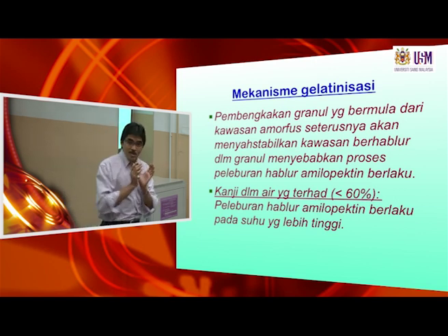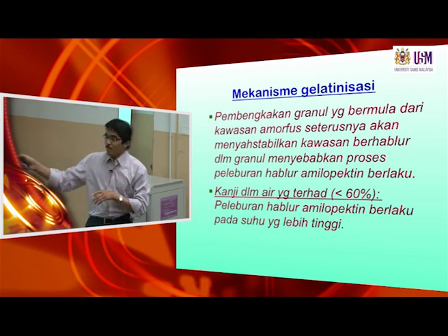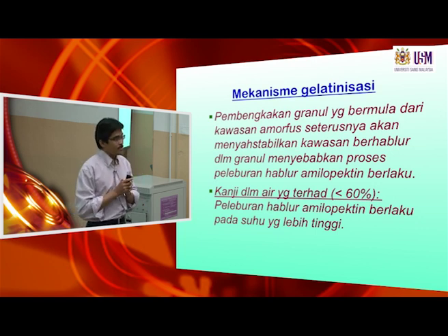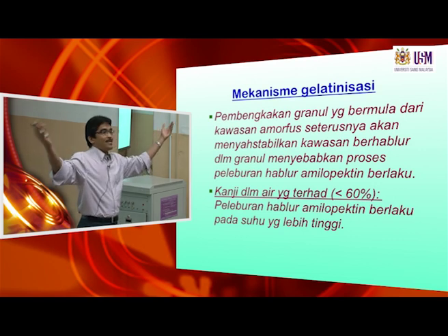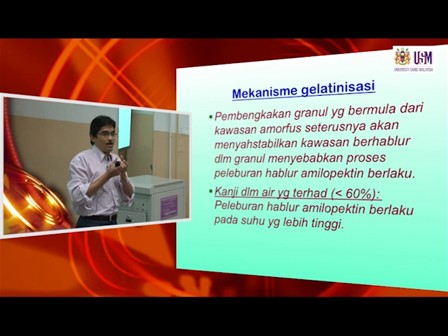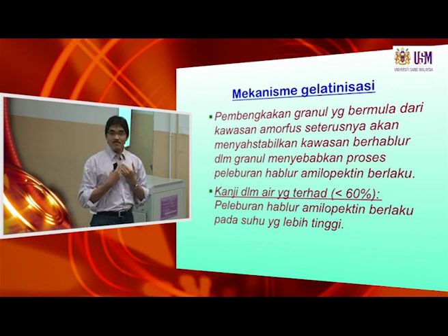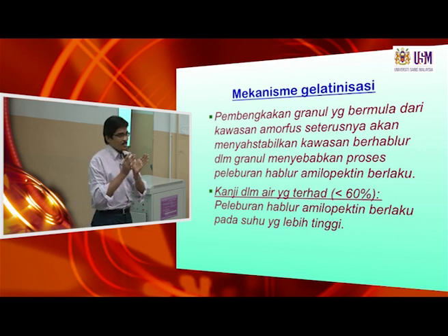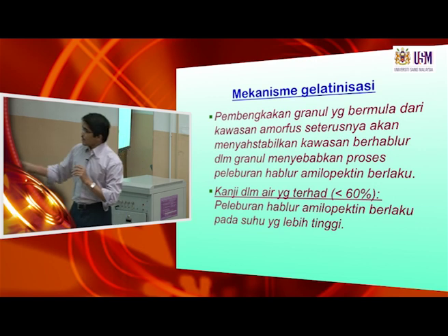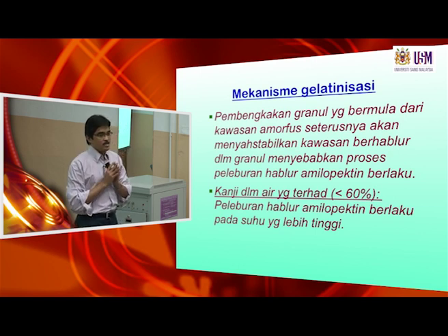Because starch is initially in a granular form, the water will have to penetrate the granule before it can be absorbed by the amorphous region in the granule. But now if you have sugar in the solution, the sugar is in a free form, more open compared to the granule structure, so it will bind water easier and faster than the granule. So more water will be bound by the sugar, and less water would be available for the starch granule. So in this situation, when we add more sugar, less water would be available for the starch. So the mechanism of low moisture gelatinization would now predominate. Yeah?